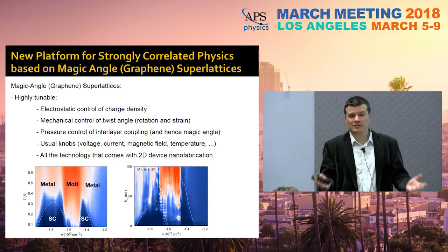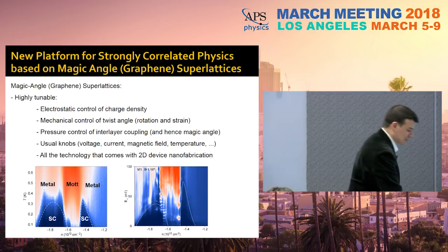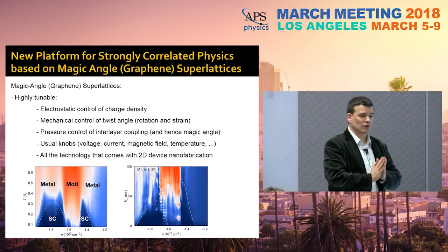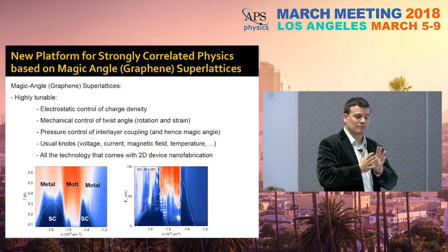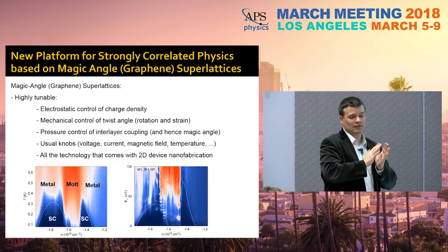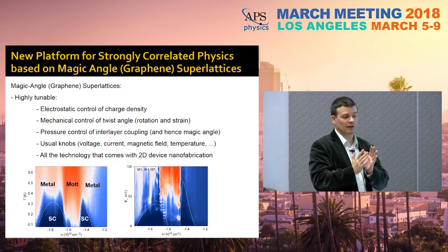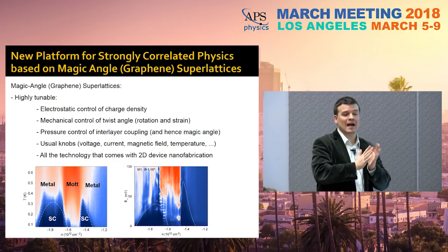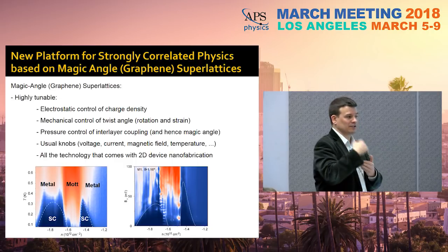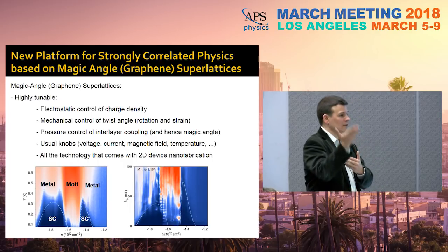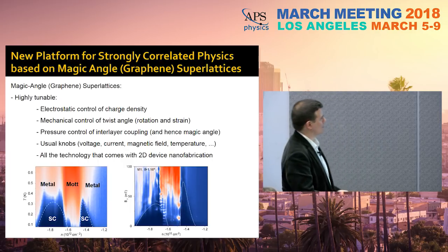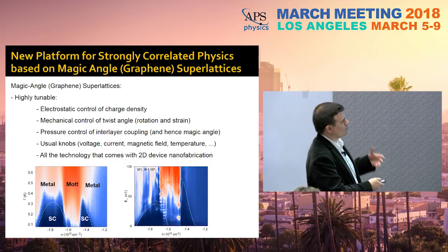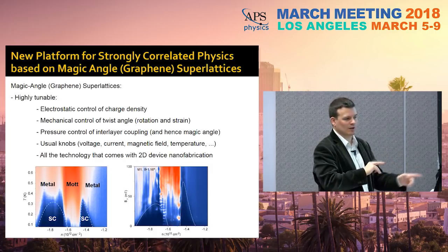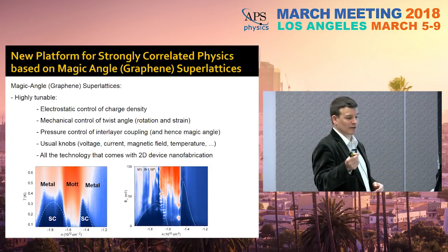Everybody asks me, how can we increase TC, okay? Well, the magic angle depends on the interlayer coupling. So if we increase that interlayer coupling, the magic angle will occur at larger angles, which will naturally lead to higher densities. And if the strength of the coupling is maintained, that will lead to substantially higher TCs, critical temperatures. We have all of the knobs that we have with nano devices and all of the technology that comes with 2D device nanofabrication. We can put local gates. After all, this is an electrically tunable superconductor, which is also useful in itself for many things.